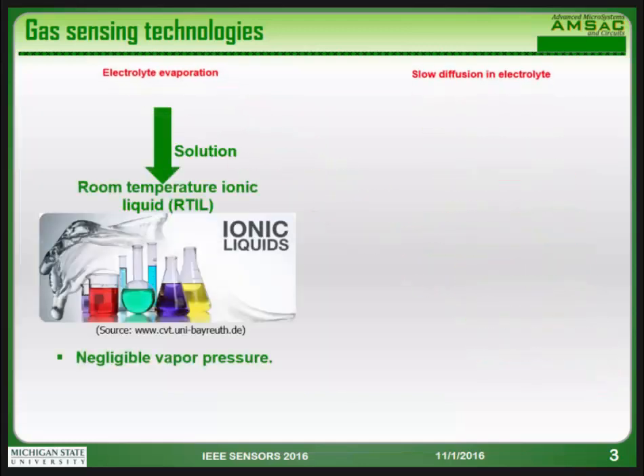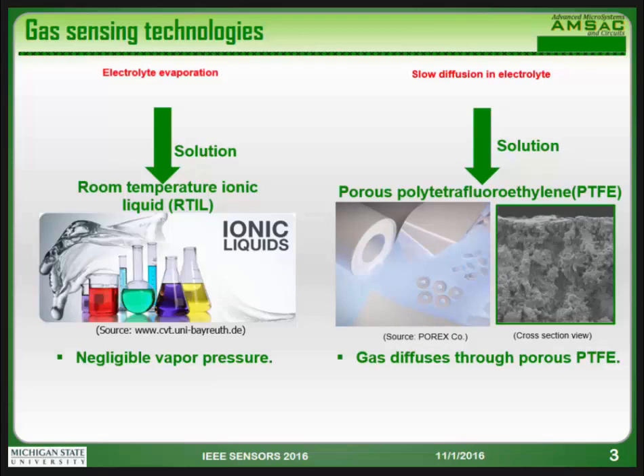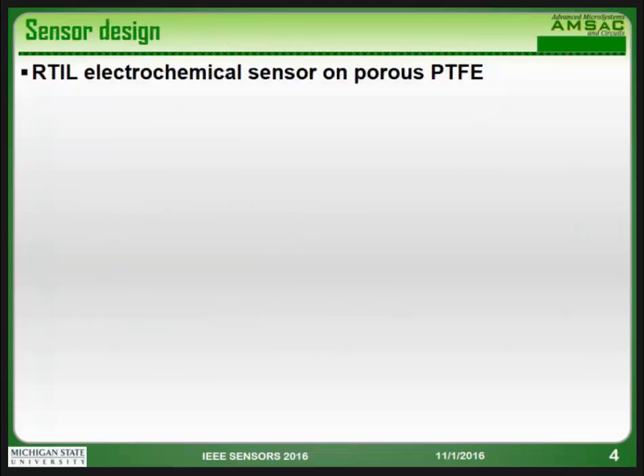So for these two problems, we came up with some solutions. The first one is the electrolyte evaporation. We use the room temperature ionic liquid, which is a liquid composed of 100% ions, and this liquid has negligible vapor pressure, which means it cannot evaporate. The other problem is the very slow diffusion in the electrolyte. So we're trying to use a porous substrate, which means the gas can diffuse through the substrate instead of through the electrolyte. By this means we can improve the response time. Based on these two solutions, we propose this room temperature ionic liquid electrochemical gas sensor on a porous PTFE substrate.